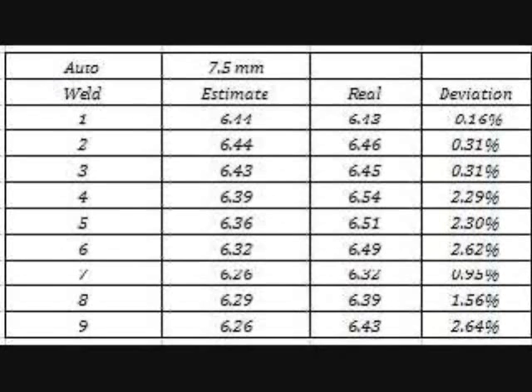After I changed the weld cap from 6.5 millimeter to 7.5 millimeter, the estimated weld size should be about 6.5 millimeter, and the real size should also be about 6.5 millimeter. The largest deviation is number 9. It's only 2.64% from the estimated.